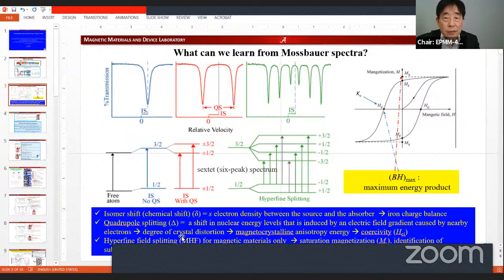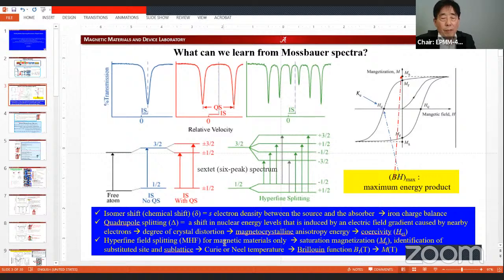And the next one is the six-line spectrum, meaning the hyperfine field. Hyperfine field means actually the magnetic structure of materials and magnetization. Identification of substitution sites, sublattices, we can do that. And also we can measure the Curie temperature or Neel temperature, like what we have done with the Brillouin function, to calculate the temperature dependence of magnetization and the temperature dependence of magnetic flux.